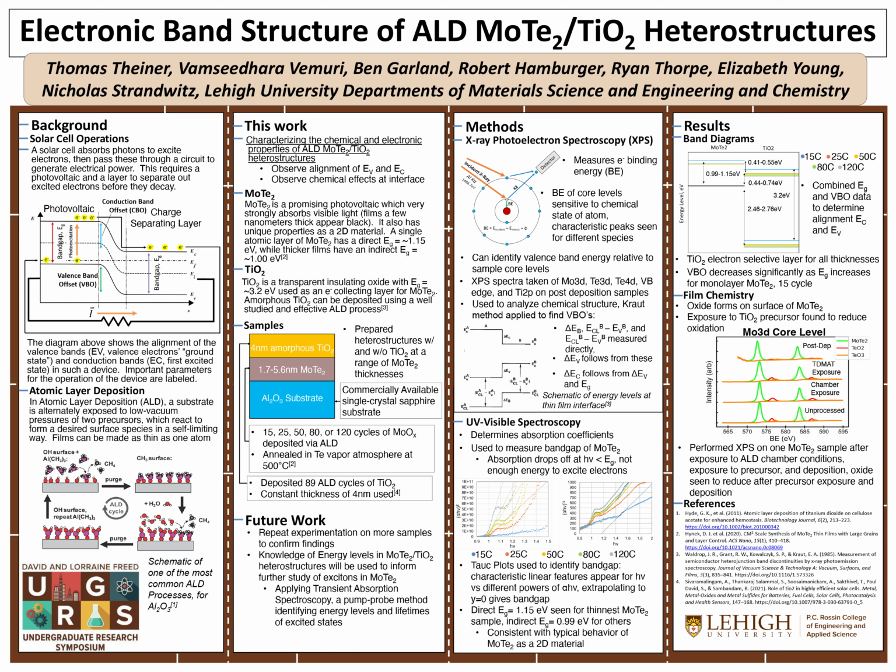So why do we care so much about this molybdenum telluride? It has a couple of properties that are really of interest to us, and it's not super well studied. First of all, it absorbs visible light very, very strongly. Even just a few nanometer films appear basically black, which is really unusual. And it also has a band gap right in the sweet spot for photovoltaics. It's around that of silicon, which is the most commonly used photovoltaic material by far, at around 1 electron volt. And this is at a level where you're not going to be letting a lot of radiation through that you don't need to, but you're also getting a significant excitation event when you are absorbing photons.